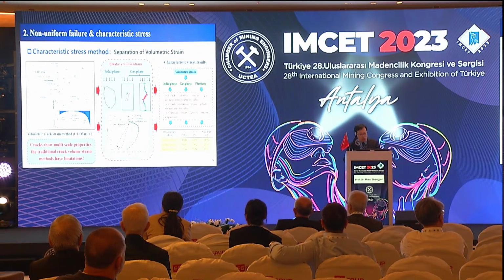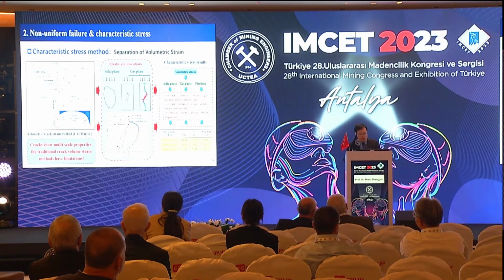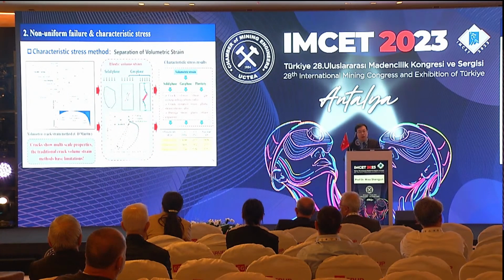The calculation results of the crack initiation stress and the crack damage stress of the siltstone using this new method were respectively 40% and 76% of the UCS.